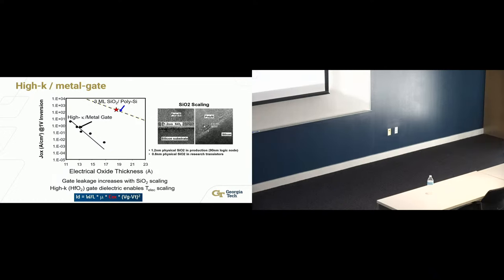And the circuit designers said it affects the circuit operation, basically, because you're not using it as a voltage control, high impedance looking into the gate. So what started off was replacing silicon dioxide with a higher dielectric constant material, a very obvious thing to do. So if you have SiO2 with a dielectric constant of 4, you replace it with high-K, which has a dielectric constant of, let's say, 20 or so. So you get a factor of 5 increase, which means you can deliver electrically the same oxide thickness with 5 times thicker dielectric. That was the idea. Well, of course, I'm not going to make it 5 times thicker. Maybe I'll make it 3 times thicker. So I go from 12 angstrom to 30 or so angstrom.